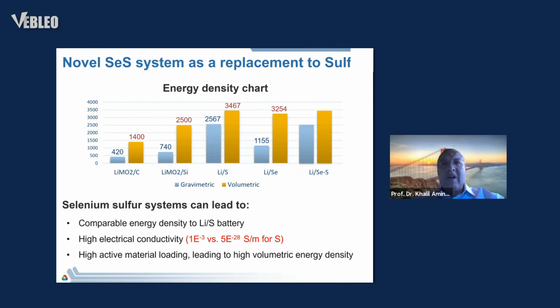Now, instead of using carbon, in most cases 10, 20, 30% carbon, that can actually impact the capacity because you are using a lot of inactive material to address the conductivity of sulfur. We actually use selenium. Selenium is active also. It has half the gravimetric capacity of sulfur, but almost the same volumetric capacity because the density of selenium is twice that of sulfur. But the biggest difference is selenium has orders of magnitude higher conductivity than sulfur.